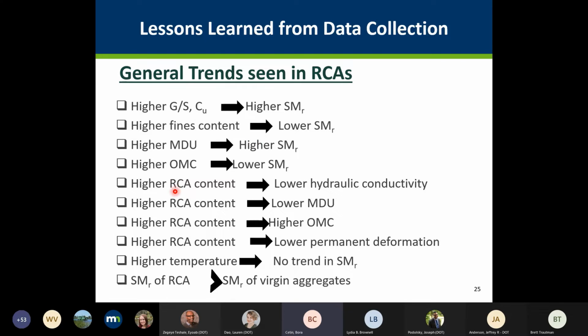And then in the next four rows, how the RCA content impacted the hydraulic conductivity, compaction characteristics, and permanent deformation of these materials. So, of course, higher RCA content caused lower hydraulic conductivity, lower maximum dry unit weight, and higher optimum moisture content of the materials, because when you mix these RCAs with regular granular aggregate bases.